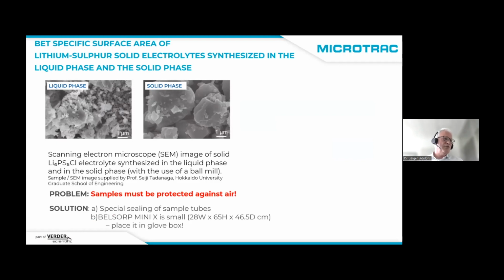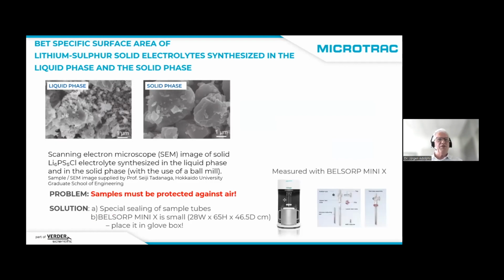So there are two ways. Either we use special sample cells, which is shortly shown here, where we can put in our samples under protective atmosphere, maybe in the glove box, seal them, and then put them in our machine for the measurement. Or, since the BELSORP Mini X is a very small instrument, only 28 centimeters in width, 65 in height, and roughly 47 in depth, we can place it also in the glove box.